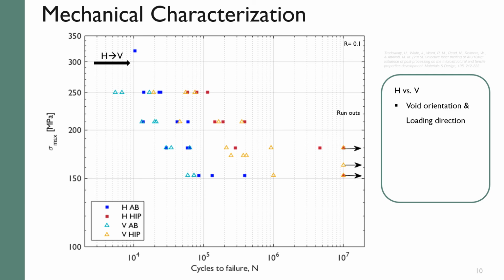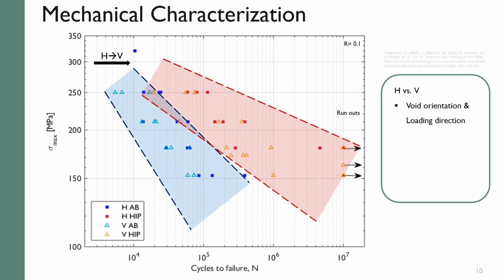And when we compare as-built, the blue ones, with the HIP condition, the red points, we can see that HIP samples have higher fatigue performance as they run for a larger number of cycles compared to as-built samples at the same stress levels. Since the grain sizes were similar, this can be attributed to the pore elimination thanks to the HIP treatment.